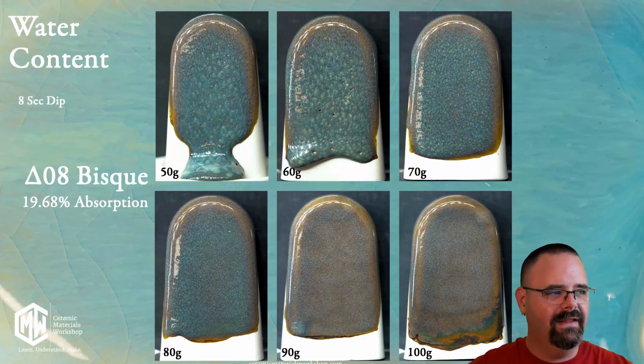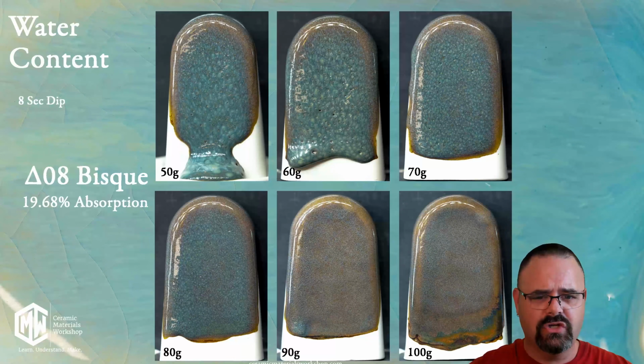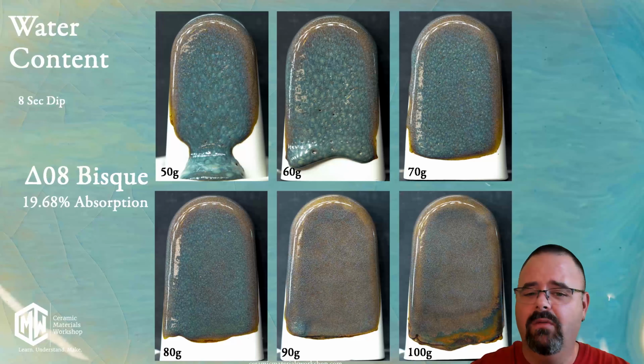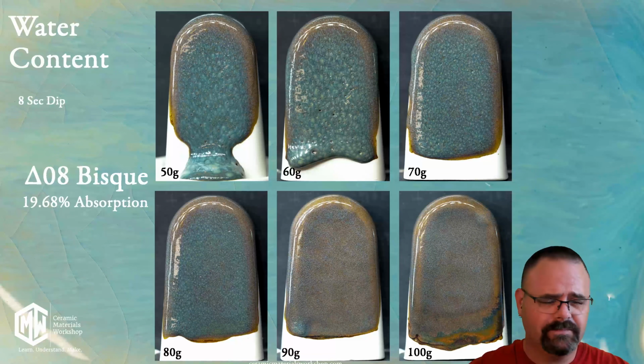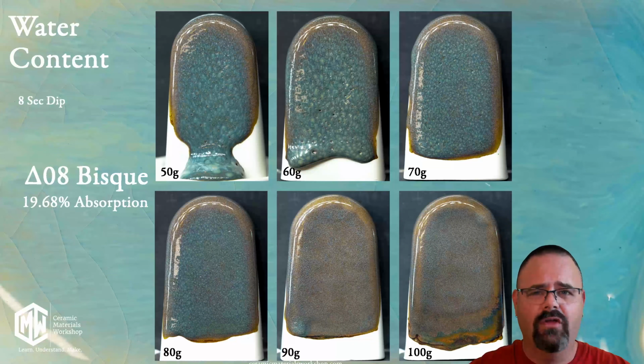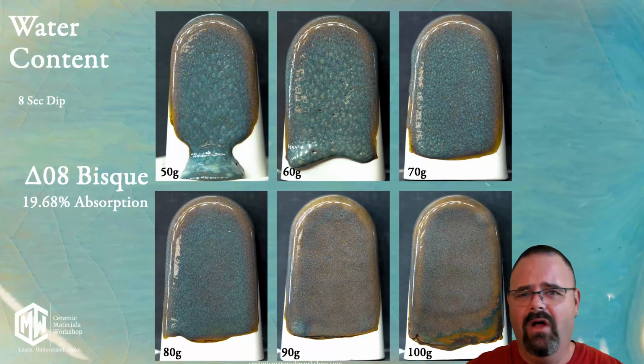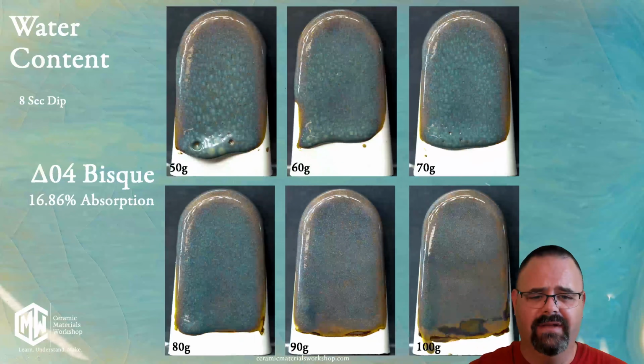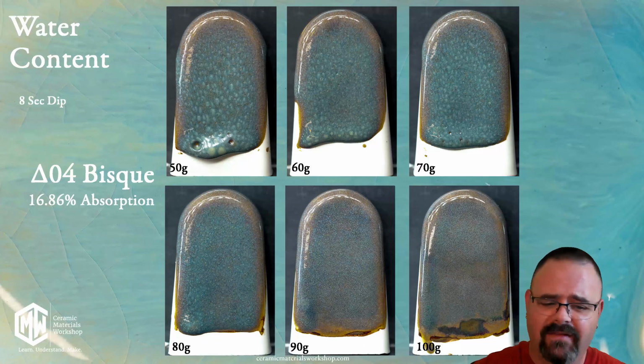Again, this is really why water content should be part of your formula. You should always be mixing with a consistent water content along with a consistent bisque temperature. These types of changes, although they may seem minor, will give you huge variations in the quality of glaze application that you get. This is the same test, though, with a cone 04 bisque.